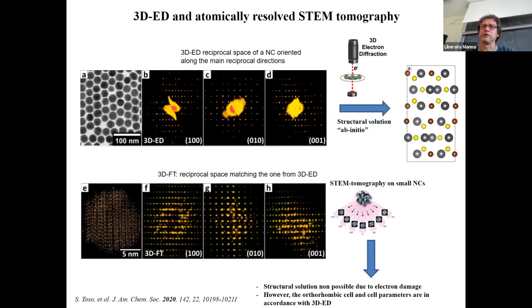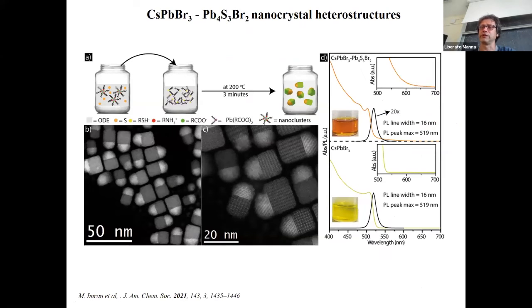These by themselves are not very interesting, if it weren't for the fact that we were recently able to grow heterostructures out of these materials with perovskite. So the synthesis is a little bit elaborate. We start from pre-synthesized clusters of halide perovskites, and we inject into these clusters all that is needed to nucleate and grow the chalcohalide. You end up forming this beautiful heterostructure where the brighter domain in STEM is the chalcohalide.